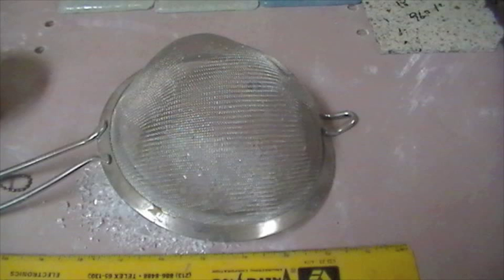If you get a sample of crushed glass that includes fines, I think it's generally wise to remove the finest glass for two reasons. First, the fines make the final product opaque, but more importantly the fines from any crushing process contain most of the dirt.